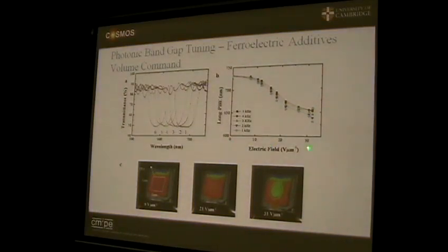Apply the electric field, and then you go down from the red wavelengths, which can be as high as near infrared, in fact 730 thereabouts, down, in this particular laser, to about 680, 640. You can switch from red to green. So you can switch your wavelength output of your laser system from red down to green, providing you've got the right dyes in the system, providing you've got the right chiral nematic. Because again, what's important is that the shape of the band doesn't alter to any significant amount, the half-width. So you maintain the quality factor, the Q factor, of your cavity.